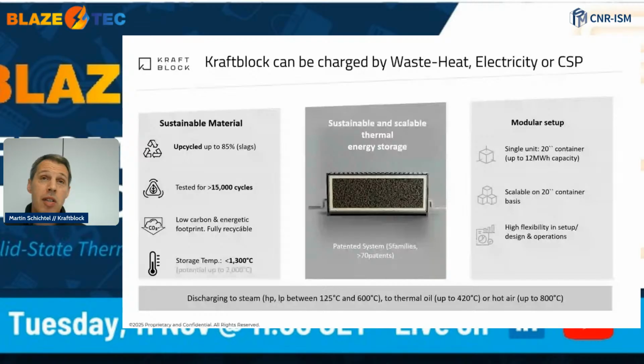The storage material itself could go way beyond 2000 degrees. So why do we limit ourselves to 1300 degrees? Again, keep it safe and simple. If we go higher than 1200, 1300 degrees C, the process architecture changes, the system setup changes, the integration to the customer changes, and there are just very few applications higher than that temperature level. So with this temperature cap, we could cover roughly 96% of the applications in industries. That's why we're quite fine with that, especially thinking about commercialization and standardization.